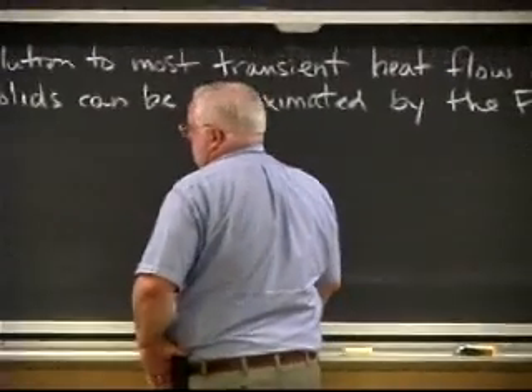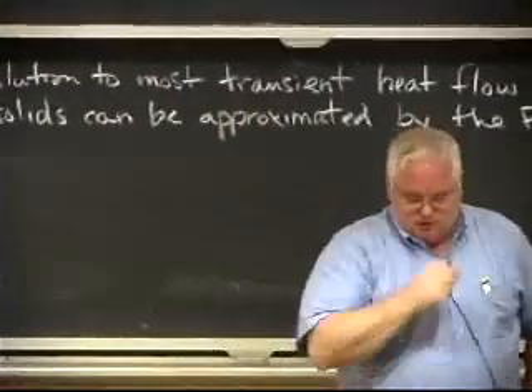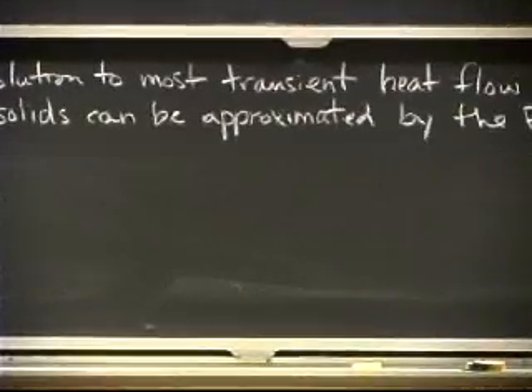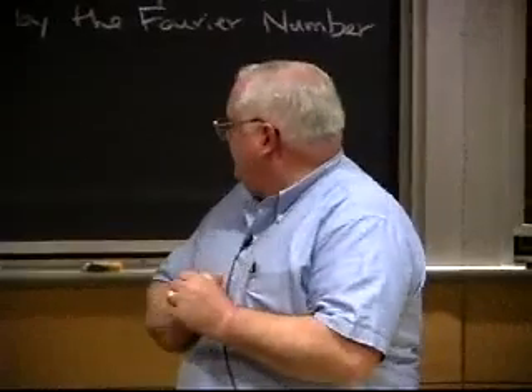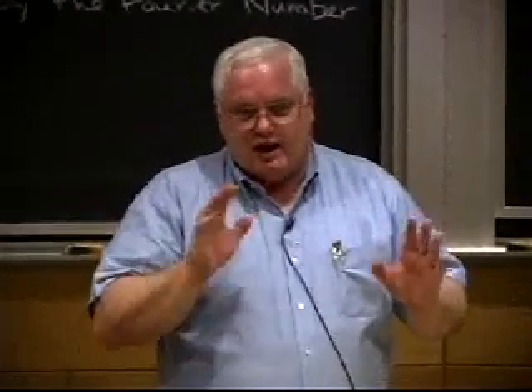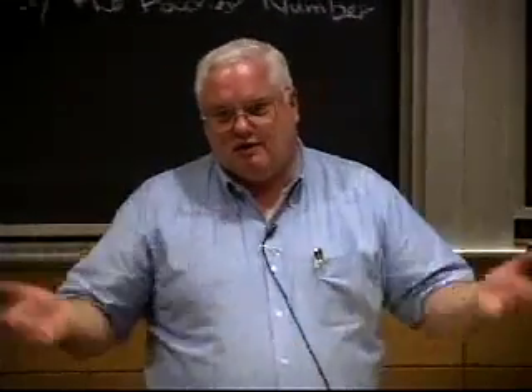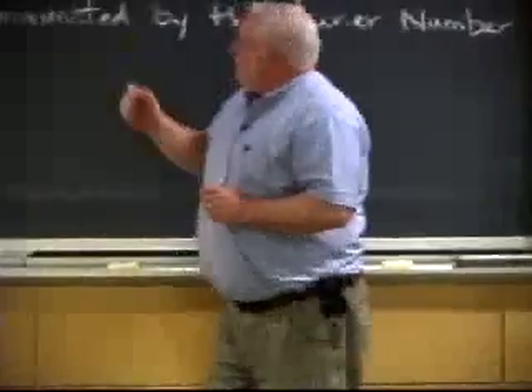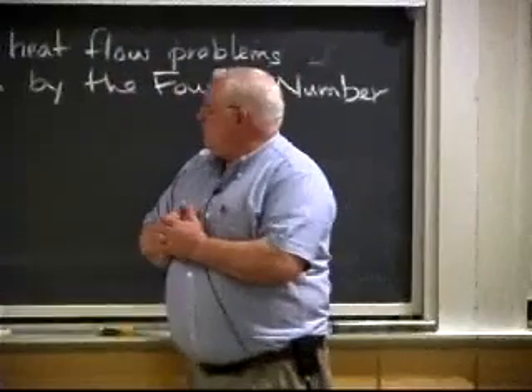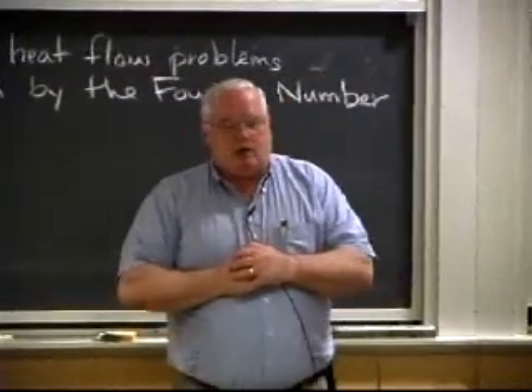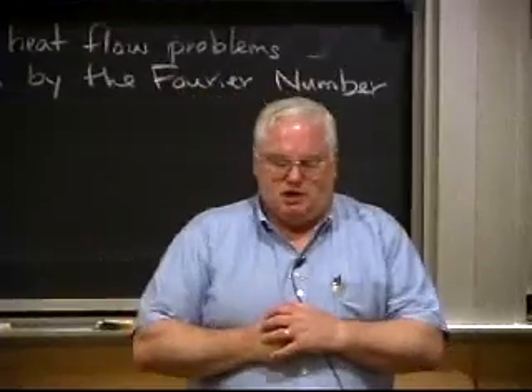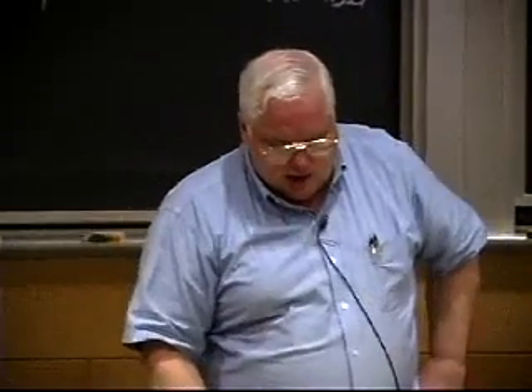I should switch these. Last time we talked about the Fourier number, which is x over the square root of alpha t, where alpha is the thermal diffusivity of the material. And I mentioned that the solution to most transient heat flow problems in solids, okay, this doesn't apply to liquids or gases, because then you get convection going on and things get different, and the alpha value changes. But in solids, which we're often dealing with in a welding process, you can approximate it by the Fourier number. You can get a very close solution by just looking at that dimensionless number.